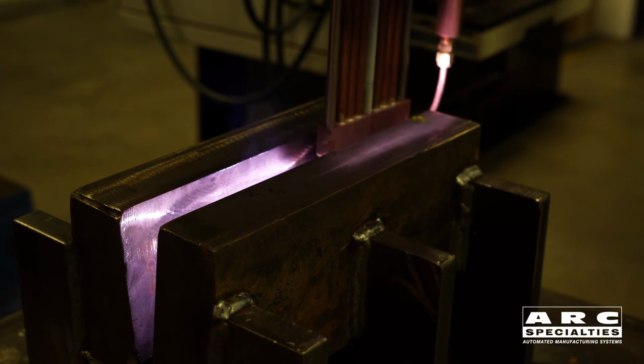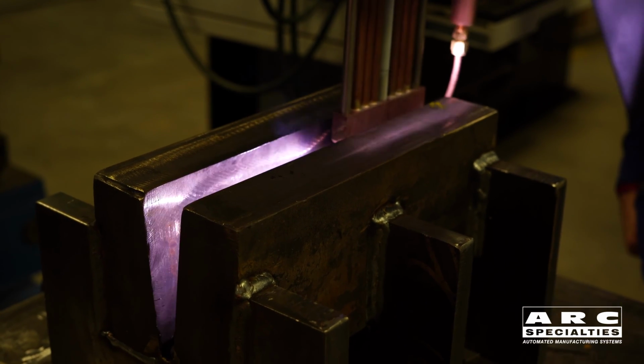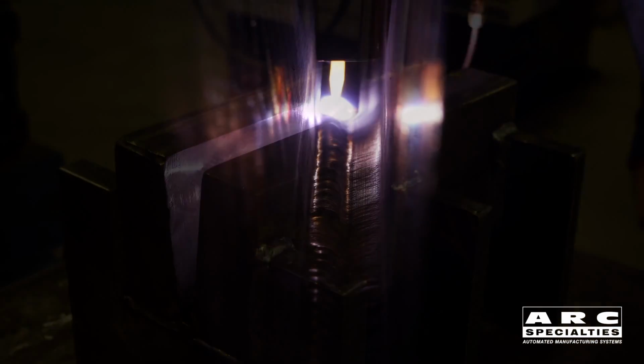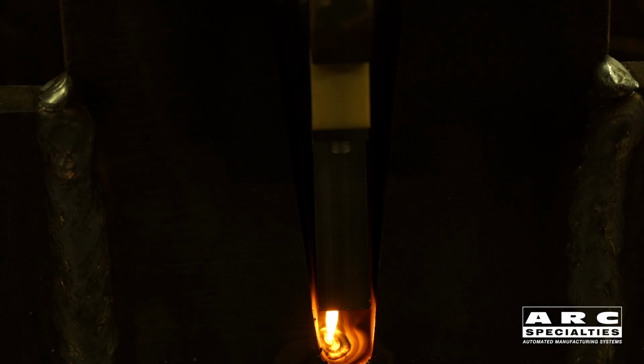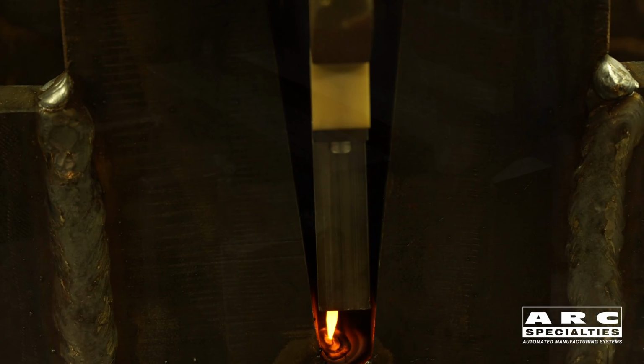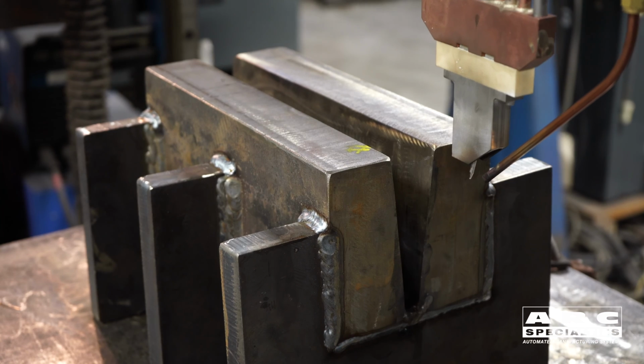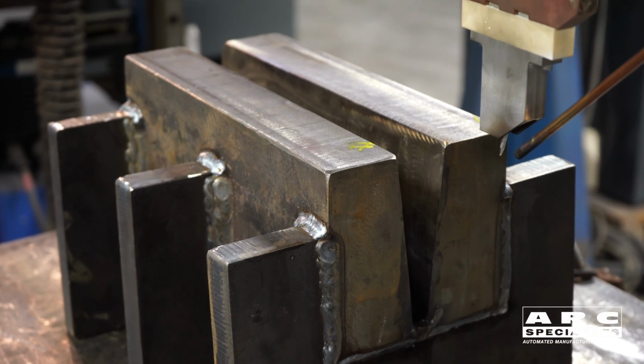This high frequency oscillation of the arc actually improves wetting of the walls of the weld joint, and it also enhances what is called weld follow, which is the ability of the weld puddle to progress. So if you're welding heavy parts, and I'm talking about anything from a couple of inches up to a couple of feet, you probably should call us, and we should discuss whether or not narrow gap welding would be appropriate